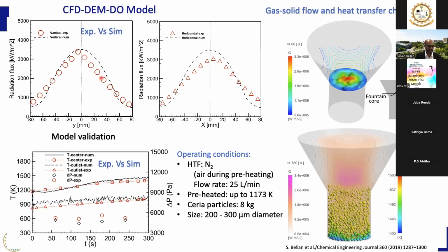And in this graph, you can see the central bed temperature, the pressure drop of the bed, and the gas temperature at the outlet. They have been compared here with experimental results. And as you can see, a reasonable agreement has been achieved between experimental and simulation results. So from this model, we can obtain detailed heat transfer, mass transfer, and radiation transfer characteristics.